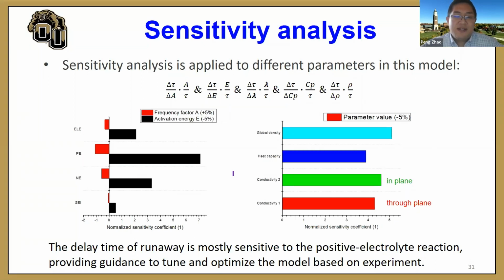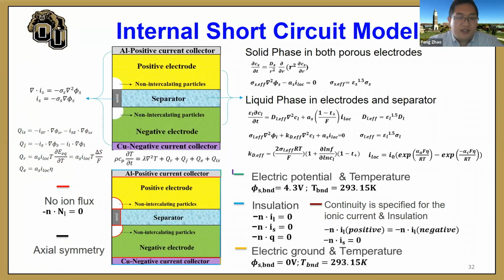And the second question I raised is, during a typical internal short circuit, what is the heat release rate? Will that be able to satisfy the critical limit for thermal runaway that we have just identified? So we built a multi-physics model by considering only 1 layer of battery: positive electrode, separator, negative electrode, and we add a piece of metal bridging the positive electrode and negative electrode. And we can solve the solid phase and liquid phase, including diffusion and migration processes in the electrodes. And we consider different source terms that include an energy equation. And imposing appropriate boundary conditions, we can simulate this internal short circuit scenario, where we can get the evolution of current, voltage, and heat release rate.